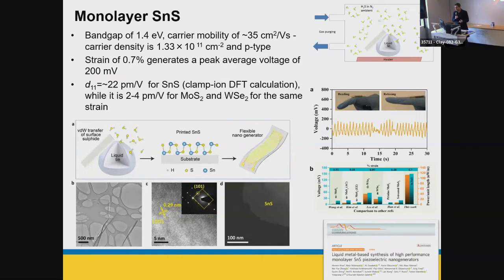We did the measurement. Mobility was very high, 35 cm squared per volt second, one of the highest P-type two-dimensional materials ever reported in mobility of holes. A band gap of 1.4 electron volts. You can imagine you can use this for many electronic applications because we have access to lots of N-type two-dimensional material, but P-type obviously don't have access to high mobility. This one can allow you to make the right LEDs. But more than that, also piezoelectricity of this material was very high, 22 picometer per volt.